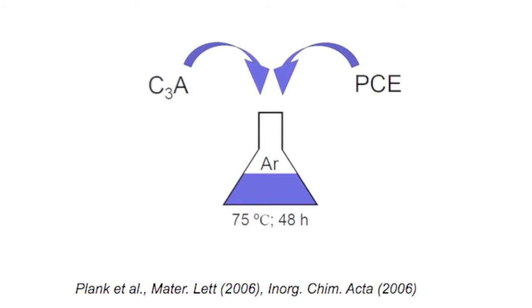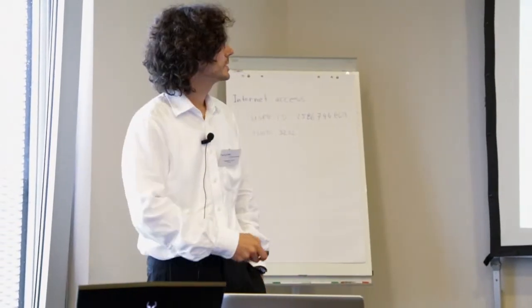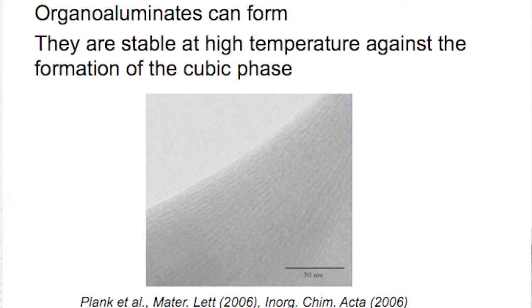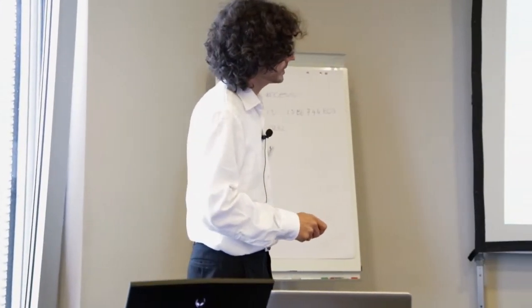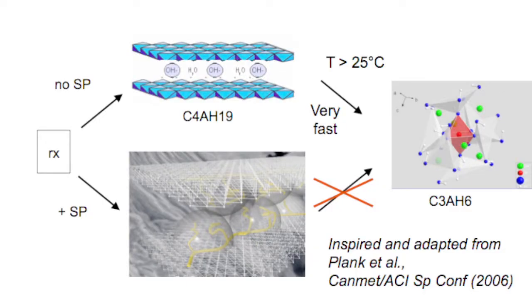So there's been various efforts to try and understand this process. One of these has taken place at TU Munich. There's been a lot of work there that was not in the core project, but I mentioned their initial main approach, although they have taken other approaches since. So the approach there was to use C3A and a polycarboxylate polymer at 75 degrees for 48 hours and then analyze the product. And what they have found is that you find nice layered structures that you can characterize very nicely by transmission electron microscopy. They identified that these phases can form and that although thermodynamically without the polymer you would not expect the laminar phase to be stable, the polymer does stabilize them.